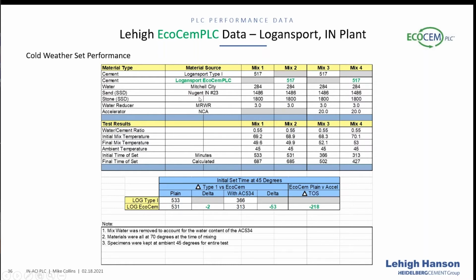All of this fits with what the industry would tell you in terms of time of set. It was good to see that temperature didn't have an effect, because we saw very equivalent times of set with untreated concrete back in our room temperature tests. Again, now we can confirm that at 45 degrees we're seeing almost exactly the same, even a little quicker set with the limestone cement. So the data that we wanted to see is what we saw.